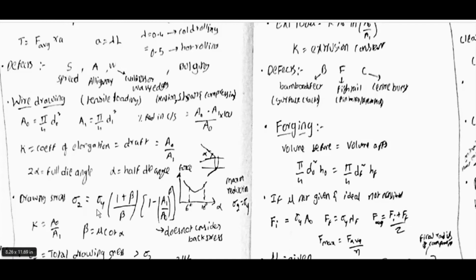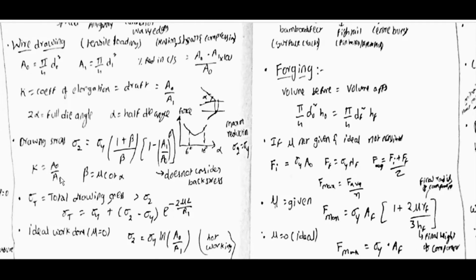Drawing stress sigma 2 is equal to sigma y into 1 plus beta by beta into 1 minus A1 by A0 whole power beta. K is equal to A0 by A1, beta is equal to mu cot alpha. Alpha is 6 to 10 degrees, it will be like this. Force versus die angle, half die angle, it will be like this; at maximum reduction, sigma 2 is equal to sigma y. This does not consider back stress.